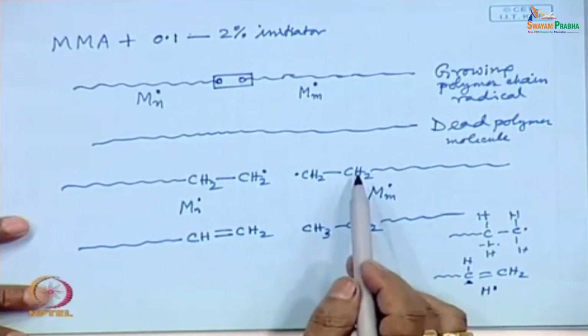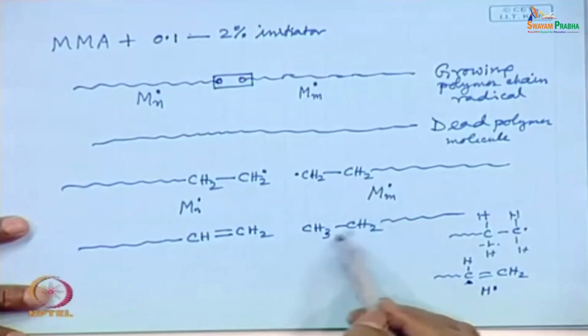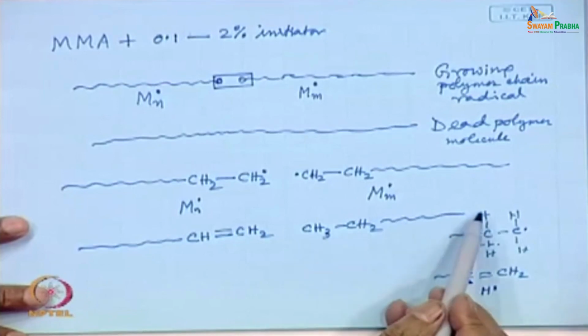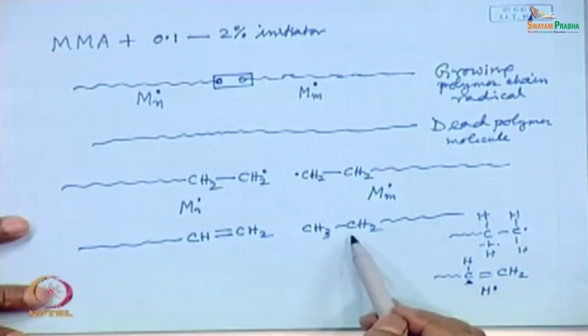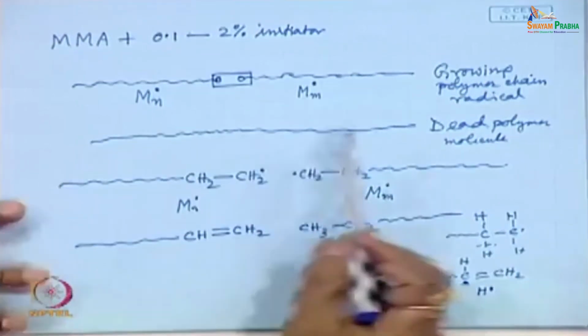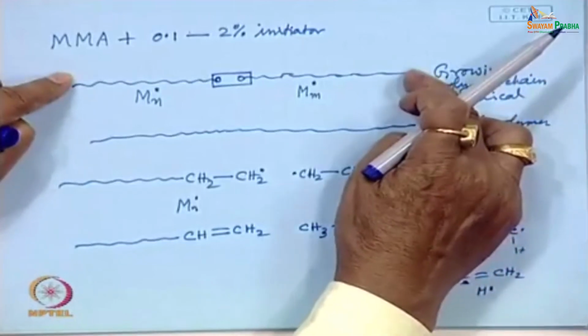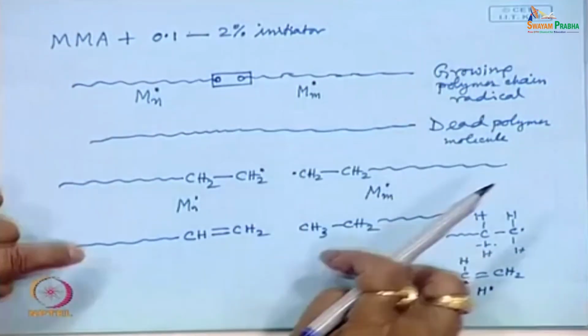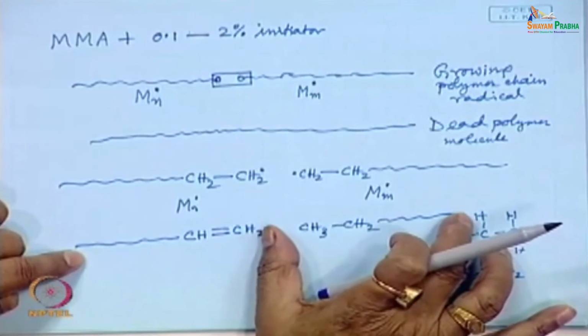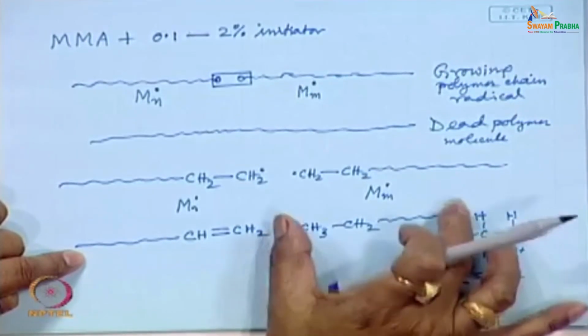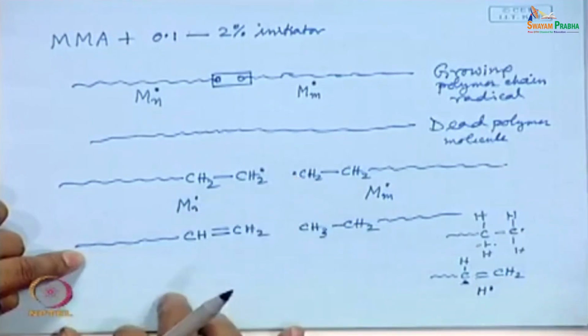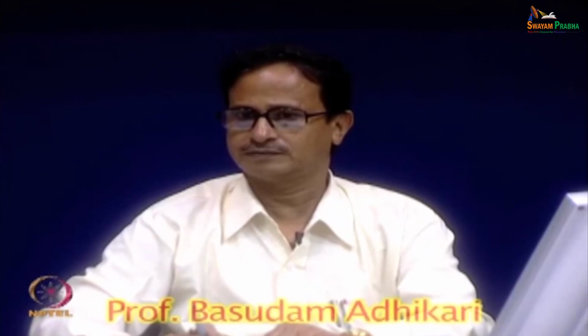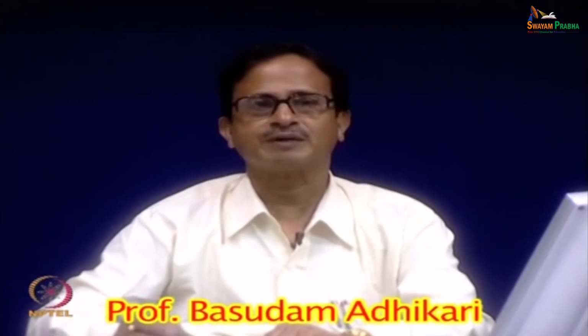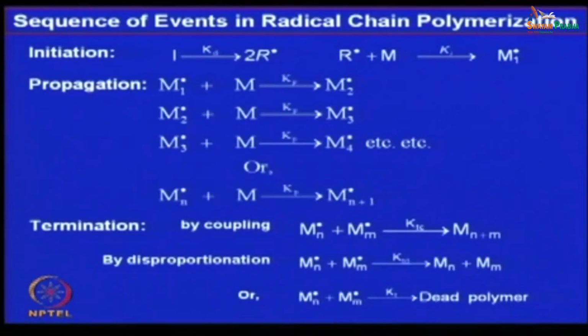Now, look at the peculiarity. In this case, this species becomes saturated, this species becomes unsaturated. Here the length becomes doubled in coupling. If they are of the same size, here the length of the polymer chain remains equal to the length of the growing chain. This is known as termination by disproportionation. So, there are 3 steps, initiation, propagation and termination, in this addition chain polymerization. Thank you very much.